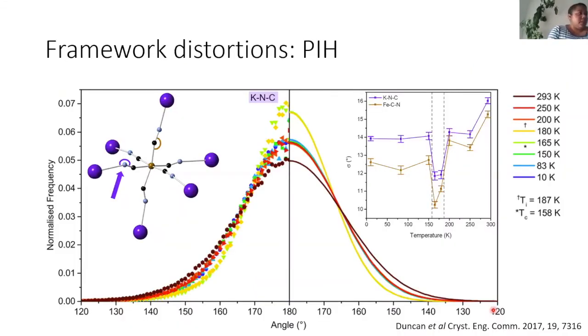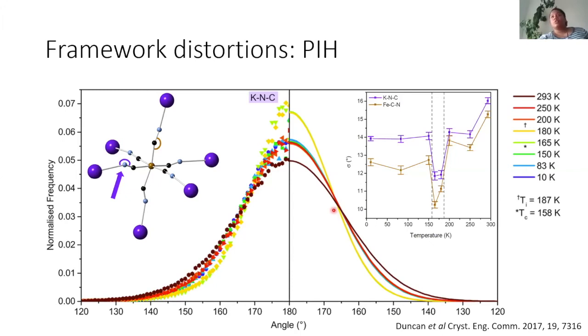We were expecting to see that in the intermediate temperature phase, the disordered imidazole ring would show some preferred orientation so that in neighboring pores they would all line up in one direction and form hydrogen bonds with the framework. We didn't see this. What we found instead was a stiffening in the metal-cyanide angles of the framework in the intermediate temperature phase. This graph shows the distribution of angles for each temperature across our 50 models of 10,000 atoms each. The spike for the two intermediate temperature phases in yellow and green shows that the framework has stiffened. Since the disordered guest molecule isn't driving the transition as we thought, perhaps we can substitute it or omit it entirely to see what happens to the dielectric response of just the framework itself.